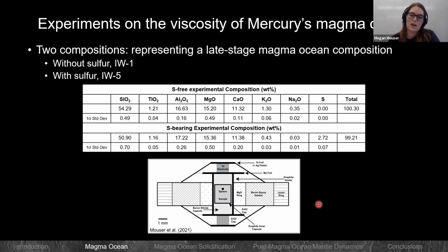This is a schematic of the experimental assembly that we were using. We put our experimental composition in here and we have a little metal sphere. It was either rhenium or tungsten carbide, depending on the composition that we were using. Rhenium would react with the sulfur, so in those cases, we would use tungsten carbide. And this is what we'd use to measure the viscosity. So this is our little experimental assembly.